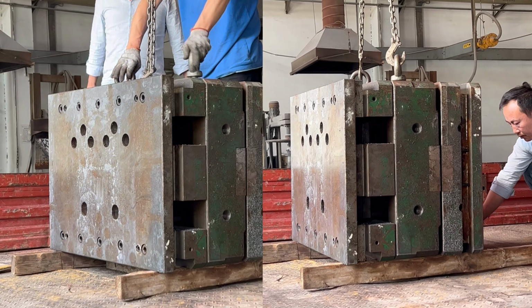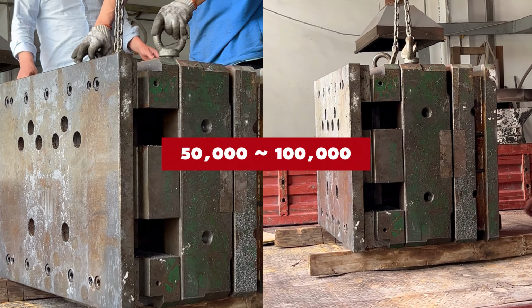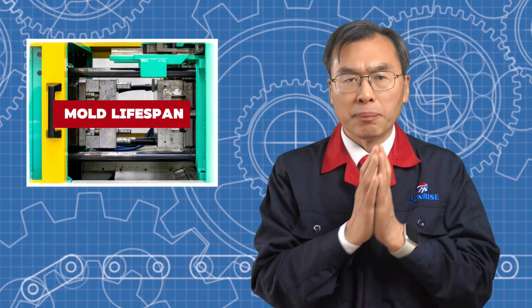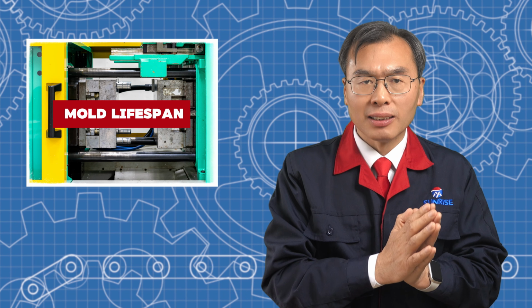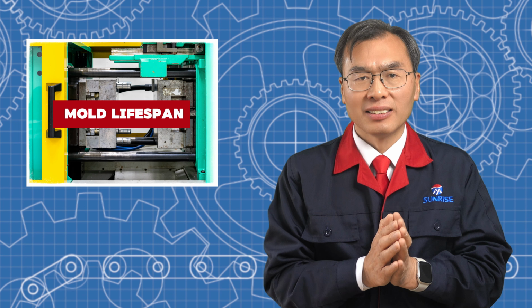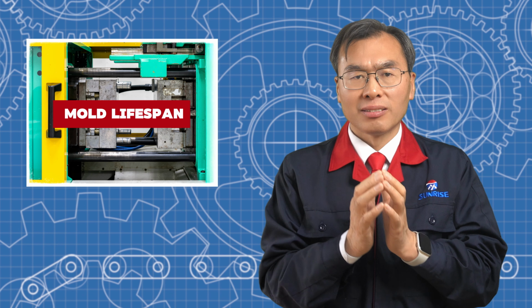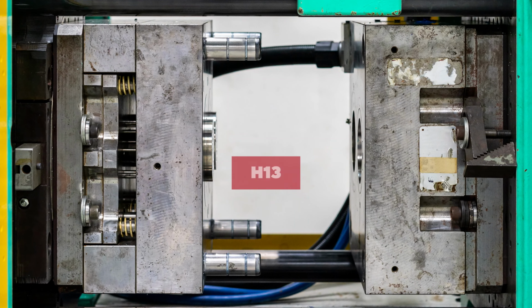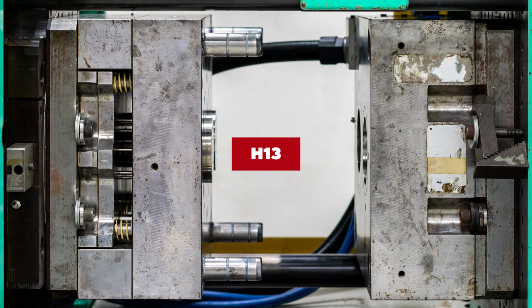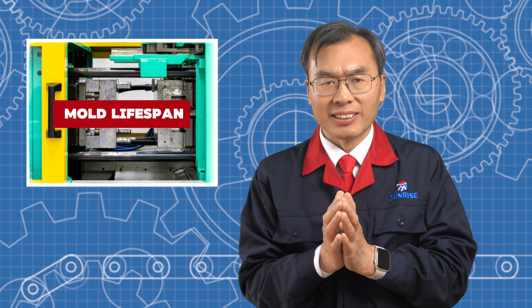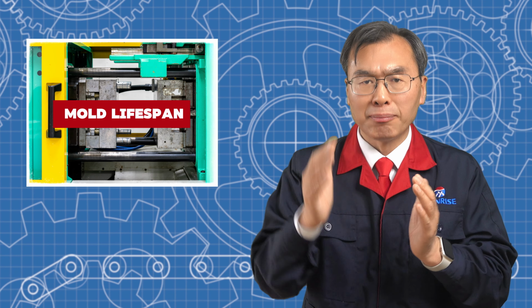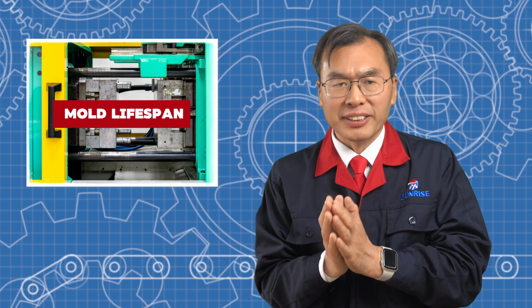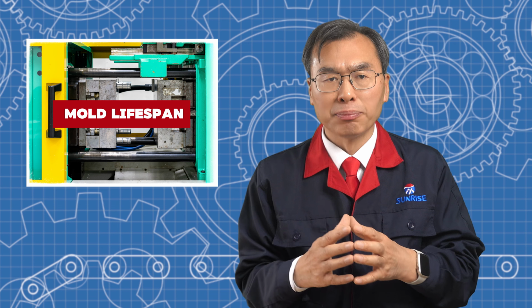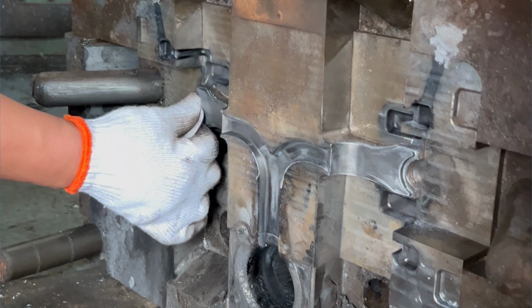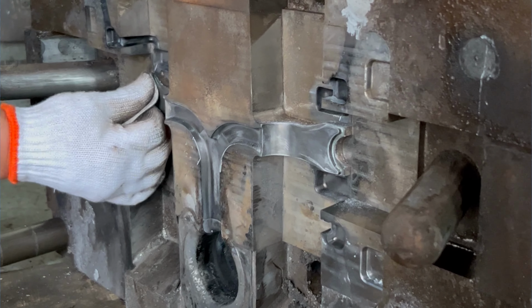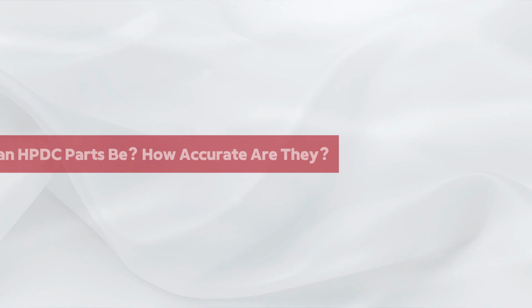High-pressure die-casting molds usually last between 50,000 to 100,000 uses. Their lifespan depends on the material, cooling system, casting settings, and maintenance. To make the mold last longer, manufacturers use heat-resistant steel like H13 and apply surface treatments to prevent cracks, keeping the mold temperature stable, preventing damage from sudden temperature changes. Controlling the metal temperature, injection speed, and pressure helps reduce wear. Regular maintenance such as polishing and repairing small cracks also extends the mold life.